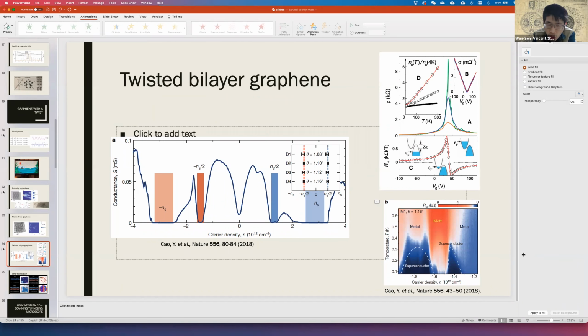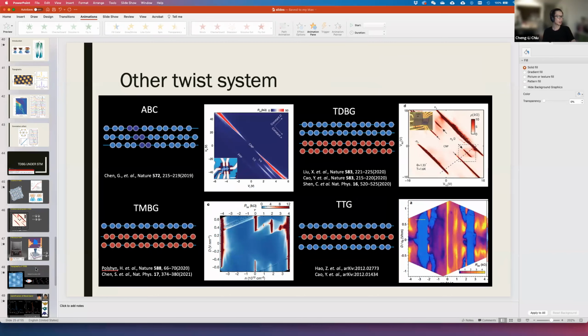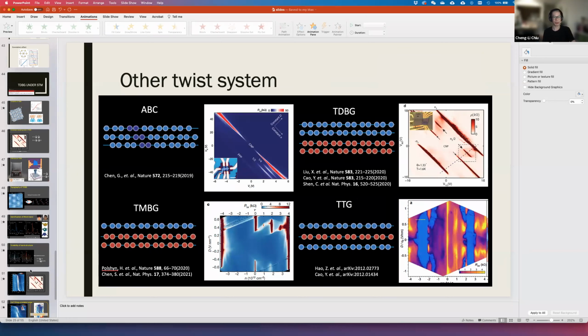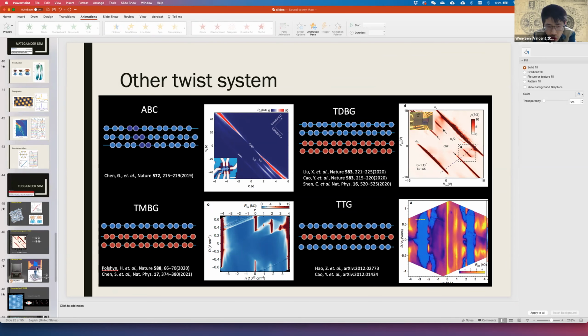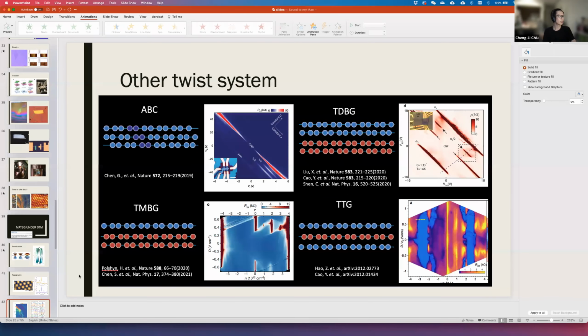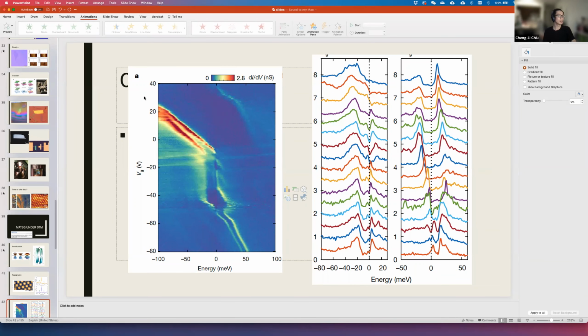So in your experience, what are the backgate voltages? For example, 17 volt or like 7 volt? So for twisted bilayer graphene, usually 40 volt. The silicon oxide wafer we are using is about 285 nanometer thick. In that case, usually 40 volt is sufficient to fill the system. And this plot is a little bit complicated because there's some tip effect, so it's making things complicated, but usually plus minus 40 volt is sufficient. And usually the silicon oxide can survive up to 100 volts. So it's more than enough to study this kind of material. I see. Thank you.